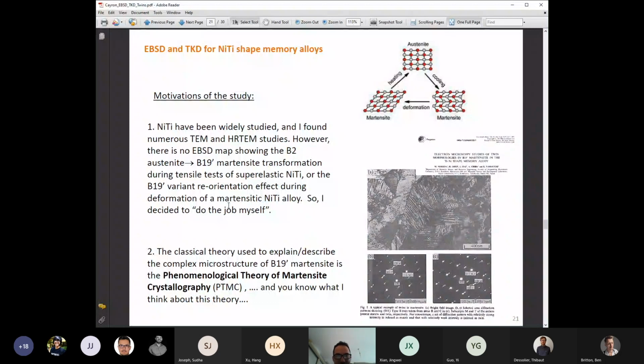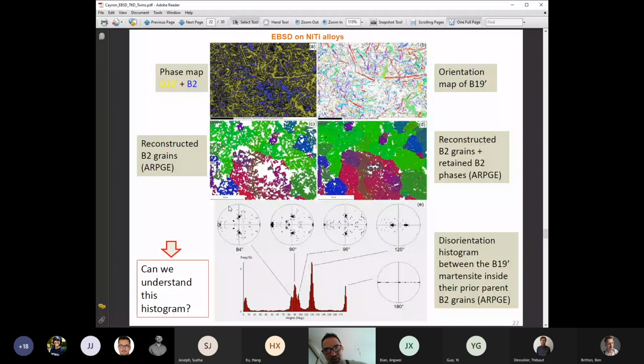So what I did, I electropolished a nitinol alloy that I bought for maybe 10 pounds on the internet. I just polished it, and I could make a map. On the first line on the right, you see a map of the monoclinic phase, that is the B19 prime phase, the martensite in the nitinol alloy. On the left, in blue and yellow, it's the phase map, where you see in blue that there is some retained B2 parent phase.